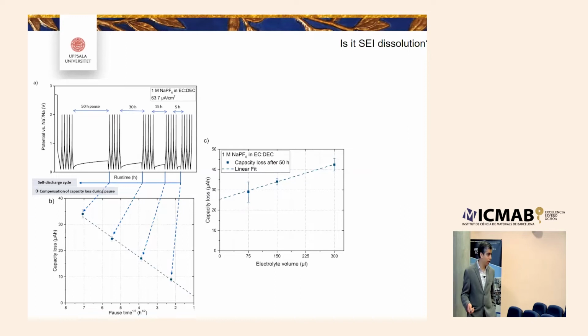From that, we concluded that there is an SEI dissolution, which basically leads to such capacity fading. So if you give it time, SEI species will migrate to the electrolyte—there is a diffusion of SEI species from the SEI to the electrolyte.